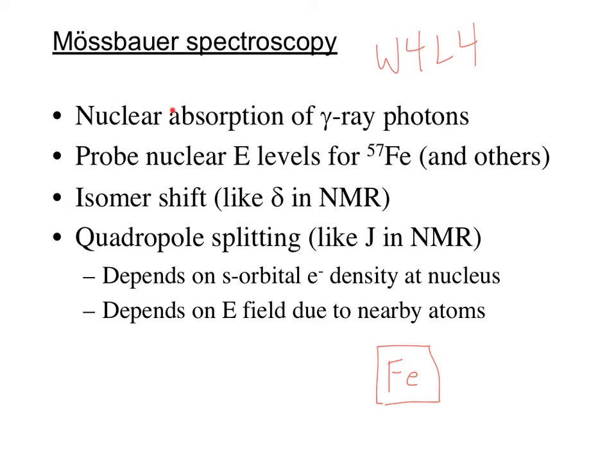You have nuclear absorption of gamma ray photons. We're looking at absorption of gamma rays causing a nuclear excitation. We can then probe the nuclear energy levels for iron nuclei, and this gives us isomer shifts, which is like the chemical shift. So the isomer shift for these species ranges from 0 to 0.1 millimeters per second for an iron 4 to greater than 1 millimeter per second for an iron 2 that has nitrogen and oxygen ligands.